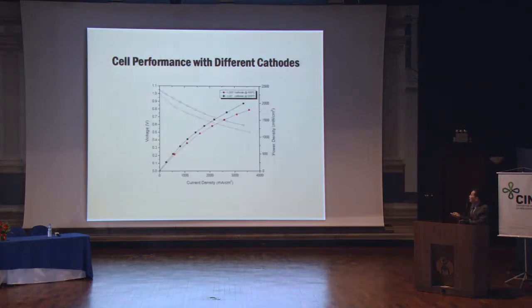We even get a better performance with a different cathode material. And here we show the performance between the LSCF and LSC at 650 degrees C. And actually, I didn't show it here, but one of the LSC cells at 650 degrees, we got about 3 watts per square centimeter. I think that is the world record performance for SOFC at those temperatures.